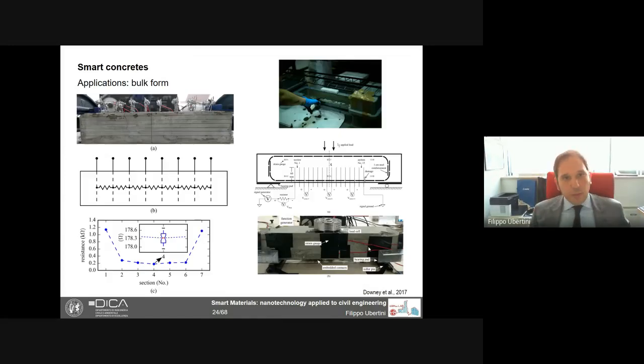Here you see, for instance, what we get from the specimen on the top left, the results in terms of resistance along the specimen. You see the blue line in the bottom left image. In the two outer contacts, we have larger resistance, but that's because of the boundary condition in the diffusion problem, in the electrical problem. And in the internal electrodes, we more or less have the same resistance. So the material is more or less homogeneous. And these values do not change in time unless there is a damage or something like this.